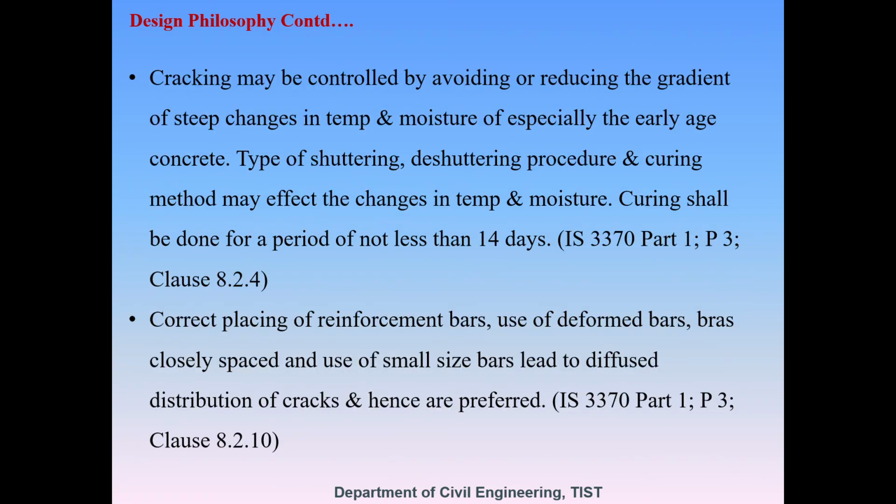Cracking may be controlled by avoiding or reducing the gradient of steep changes in temperature and moisture, especially in early age concrete. The type of shuttering, de-shuttering procedure and curing method may affect the changes in temperature and moisture. Curing shall be done for a period of not less than 14 days as per clause 8.2.4. Correct placing of reinforcement bars, use of deformed bars, closely spaced bars and use of small size bars lead to diffused distribution of cracks and hence are preferred. It is given in 8.2.10.